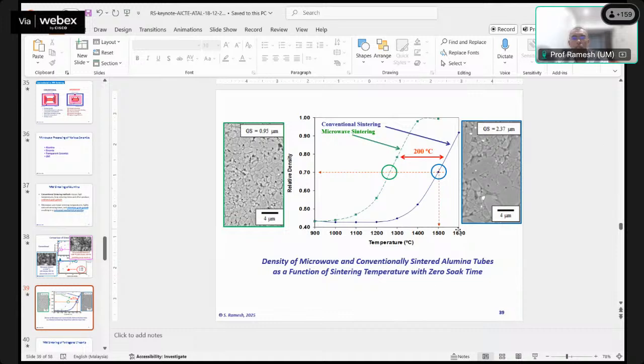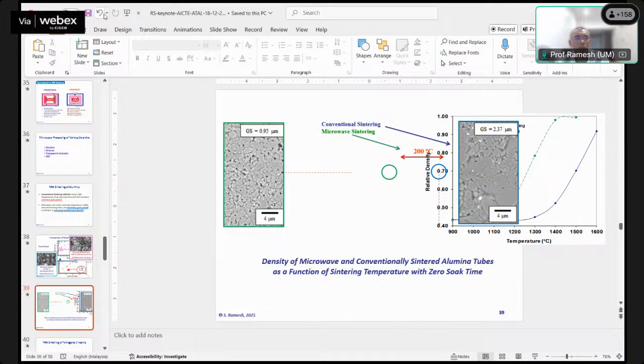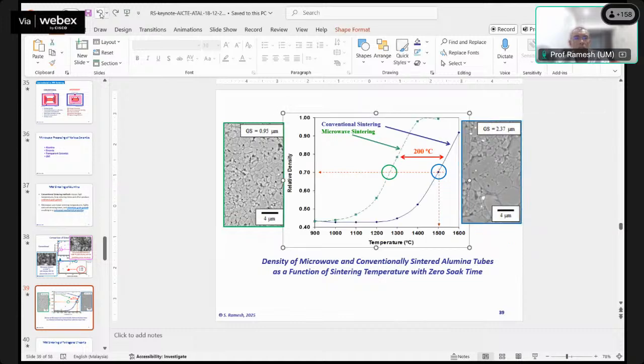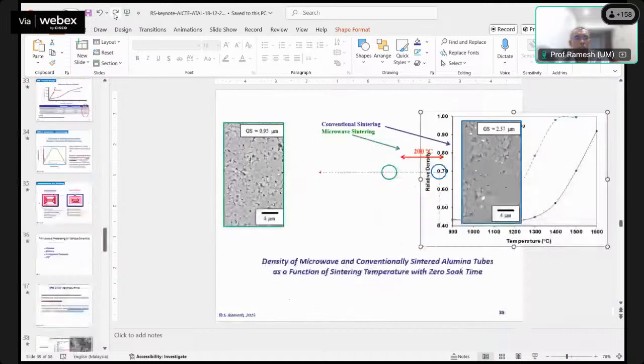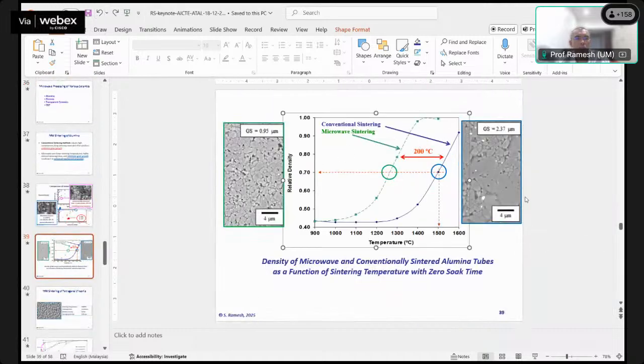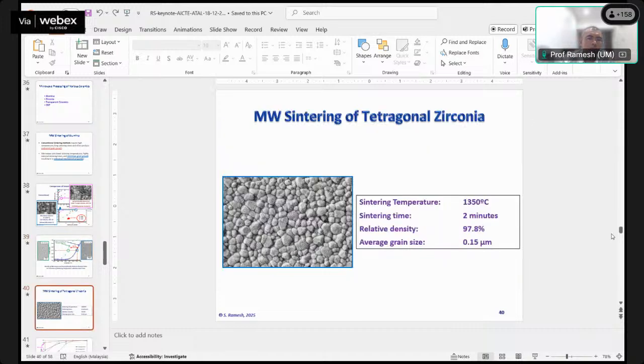All right, so this again just to show the variation in the grain structure. So as you can see, 2.37 micron for the same relative density. As you can see, when we look at the structure at 70% dense, you can see that the one with microwave is below 1 micron as compared to the one that is conventional, way above 2 microns.